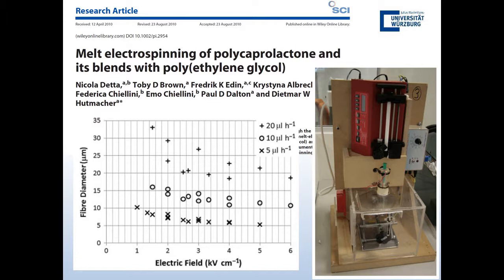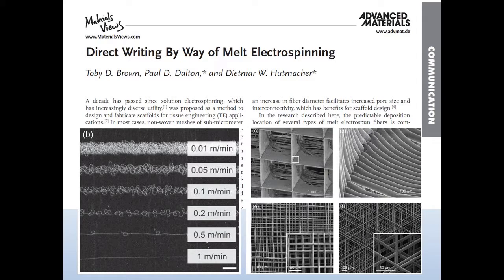But we could see as well that the fiber diameter was really dependent on the flow rate that we would deliver. And actually Nicola Detta was really important as well, because he was the first guy that didn't listen to me when I said, oh, okay, I work with the block copolymers and blend with PCL. I said, I'll just use PCL. Let's use straight PCL. And actually we found that was far more stable. And so instead of electrospinning, we started what I would call electrowriting, doing direct deposition. And this resulted in the work of Toby Brown, and this was his first paper.